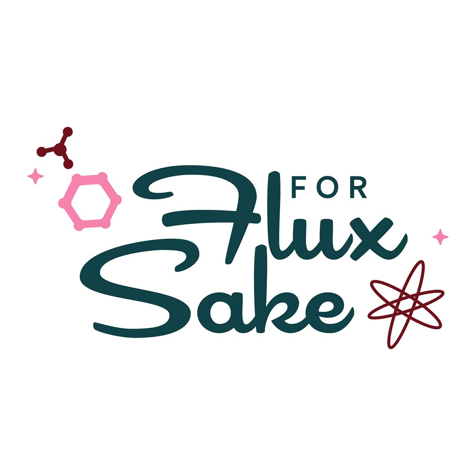My setup is at my house, and I have my own electric kiln, so I can fire any way I want to. I am using a white commercial stoneware that is advertised to mature at cone 5 to 6. I have done multiple firings and 5-hour absorption tests and have found that it needs to be a cone 7 plus about a 5-minute top hold to pass a 0.5% absorption test. Now that I've found that, I am testing the commercial glazes that I am using to make sure they will perform the way I want them to.